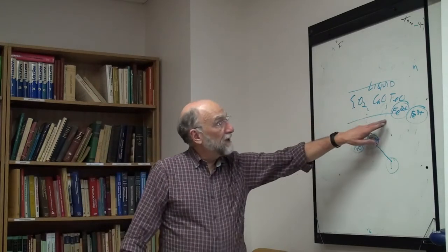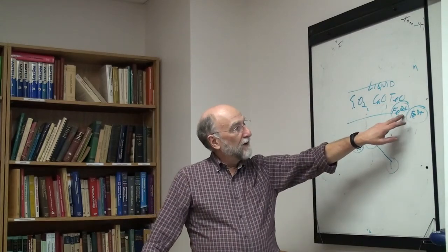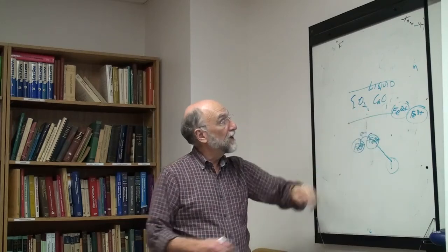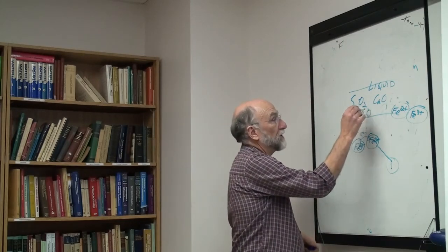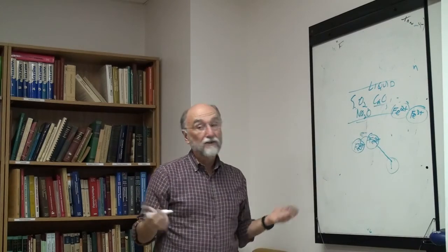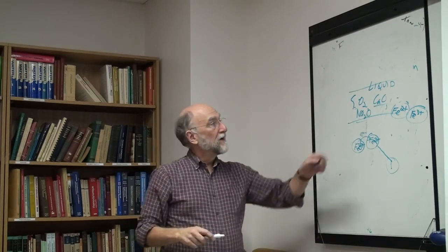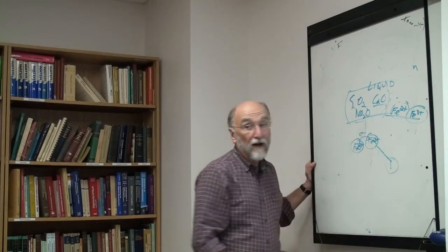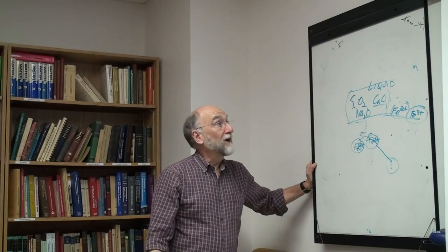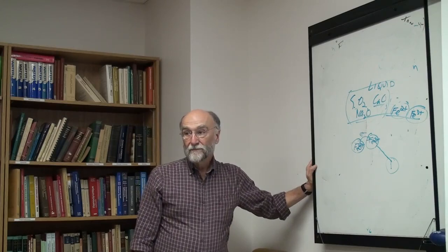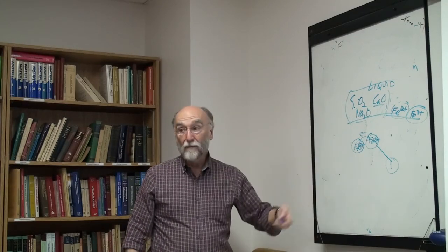So slags containing iron, or containing other ions that have two oxidation states. A slag containing only, say, silicon and CaO, and no iron, I mean calcium and sodium only have one oxidation state for all intents and purposes. These slags will be purely ionic with no electronic conduction. But if you start putting in iron, basically under any oxygen pressure, you're going to get electronic conduction. And manganese, chromium, things that have two oxidation states will give you electronic conduction.